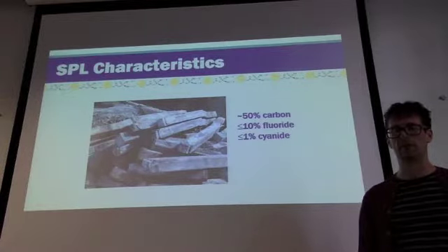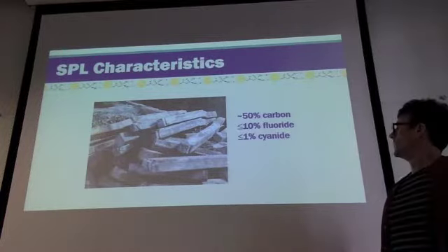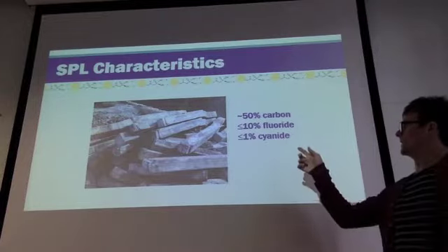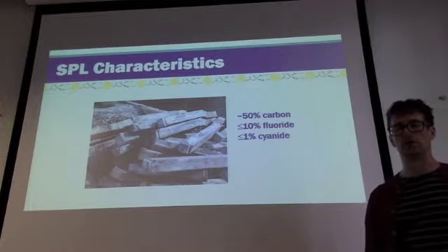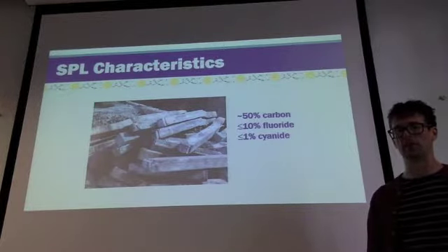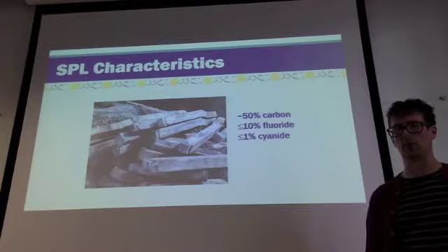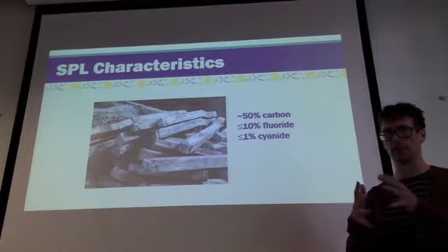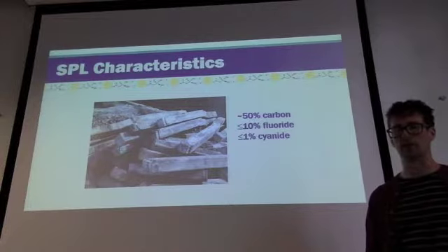Now, SPL is a highly toxic and really rather dangerous type of waste, partly because of the elevated levels of fluorides and cyanides that we see here. It also, when contacted with water, can give off a mixture of potentially explosive gases. In fact, this quite infamously led to a cargo ship which was carrying some SPL waste across the ocean for disposal, actually exploding due to an accumulation of these gases within its hull. So clearly SPL presents a considerable safe storage challenge.